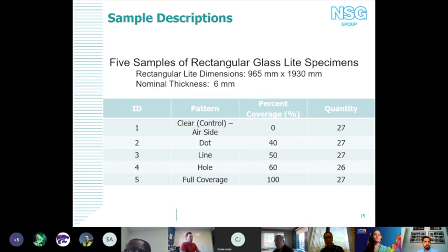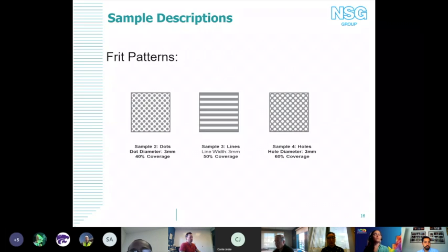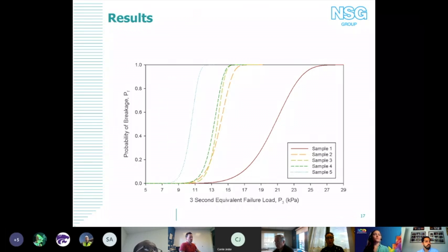What we did was we tested our control, and then we had varying percent coverages with this frit, and it was all a gray frit. So we did 40, 50, 60% coverage, and then a full coverage. Move forward, and you can see an example of what the patterns look like. We had our dots, our lines, and essentially the reverse of the dots, so we just had these holes. Again, here's another look at the distribution of them.